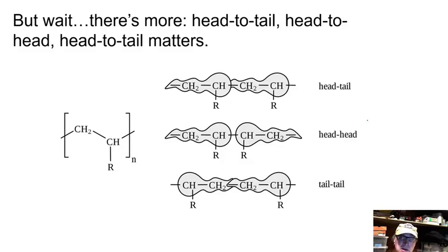This shows what I was just saying, that it's really about the electron volume. So in this slide, which I think also comes from that same Wikipedia article on tacticity, it's a pretty good article, it tries to show where the electrons are, the electron map of this. But it also shows that when a vinyl unit comes in, it really can add facing forward or facing around the other way. So here is head to tail. Let's say this is the head, and then it joins with the tail. So this is head, and that's tail, and then it's head, and the next one is tail. Now this one is head to head, and this one is tail to tail. So this can all be figured out, and all these things slightly affect the behavior of the system. They're all measured. The way we find this out is by nuclear magnetic resonance spectroscopy. And it's the catalysts that control this to a considerable degree.